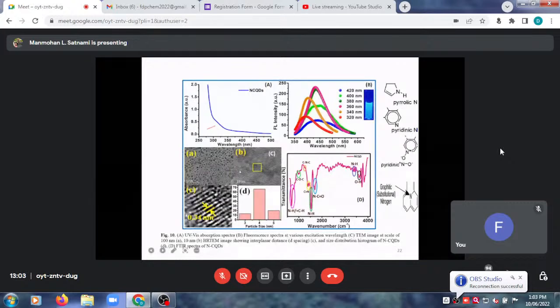So what is actually a carbon quantum dot? You can consider it a sheet of 3-4 layers of hexagonal carbon. As we know, in graphite, the difference between two layers of graphene is exactly 0.33 nanometer. So you can see here, what we were just looking at is 0.34 nanometer. Using this spacing, we can also characterize the carbon quantum dots.